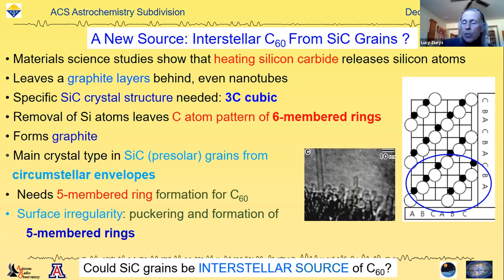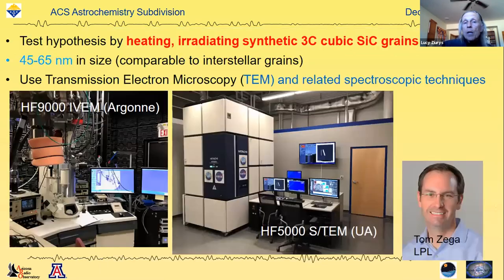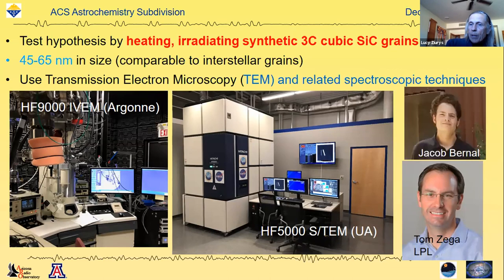So we got very interested in this, as silicon carbide with the 3C cubic crystal structure was found in circumstellar grains, and decided to do some experiments ourselves to test this hypothesis by taking model silicon carbide grains with the 3C cubic structure, comparable in size to interstellar grains, and subjecting them to shock-type conditions using a transmission electron microscope. We first did these experiments at Argonne National Lab and then at the TEM at Lunar and Planetary Lab at the University of Arizona with our microscopy expert, Tom Zega, professor at Lunar and Planetary Lab. And this was all prompted by my student, Jacob Bernal, and that's his picture right there.